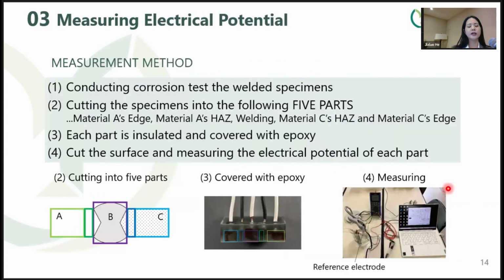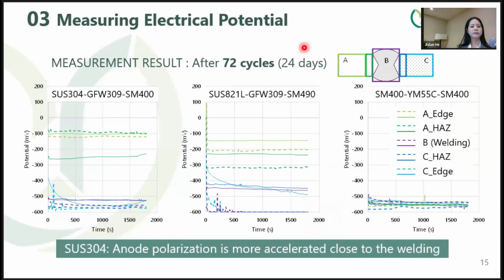Right now, that's the corrosion campaign. And at the last part, I'm sharing the electrical potential measurement experiment results. It was the first conducting corrosion test as shown below, and we cut the specimen into five parts, as shown in the left figure, and each part is covered with epoxy, and we cut the surface and measured the electrical potential as shown in the right figures. These figures show the measurement result after 72 cycles. The dash line is the initial, and the plain line is the result after corrosion.